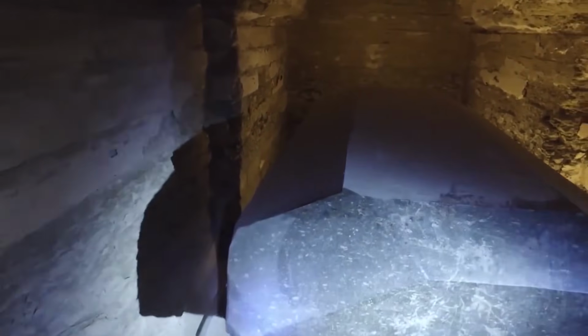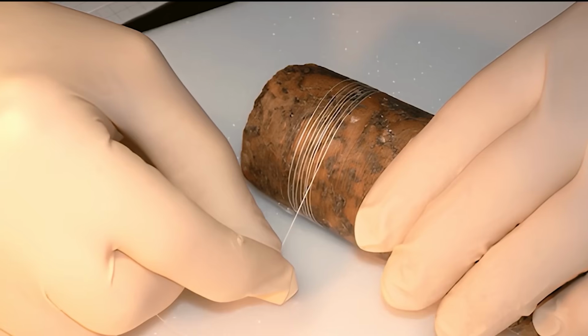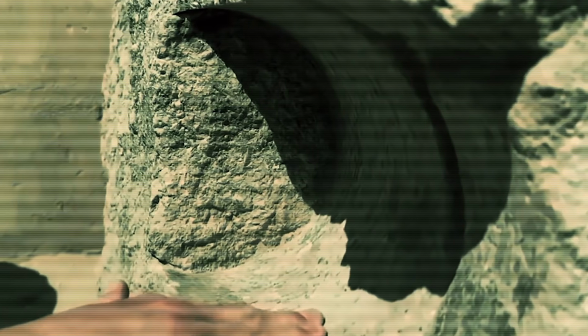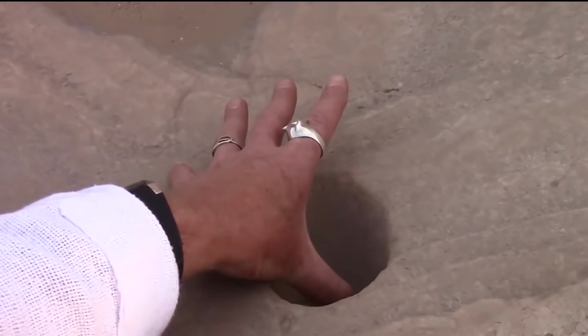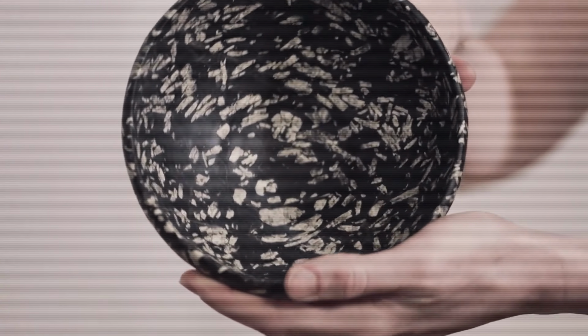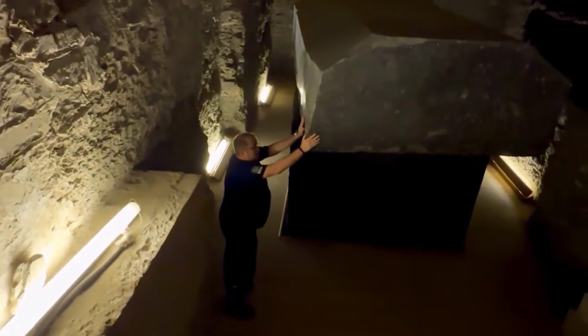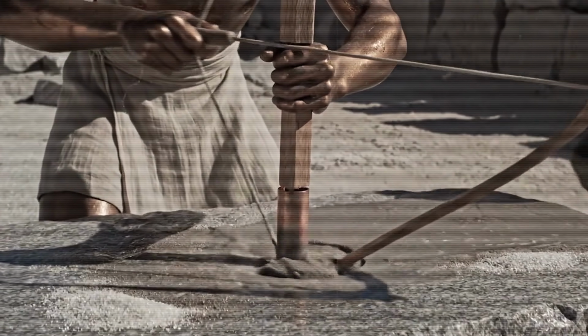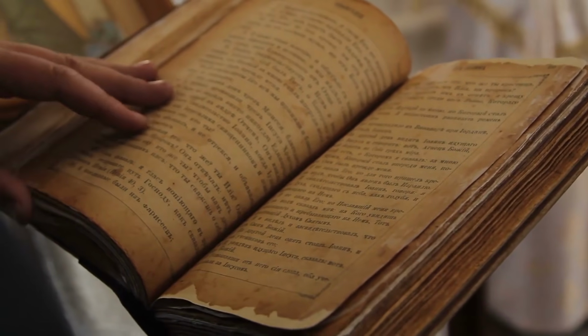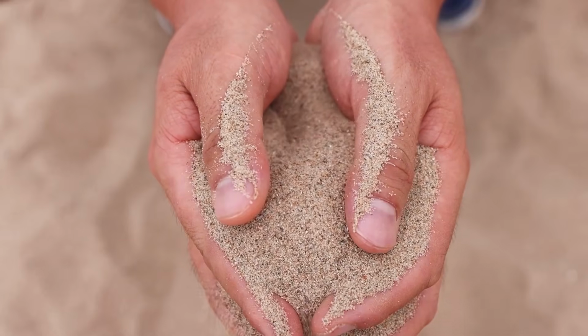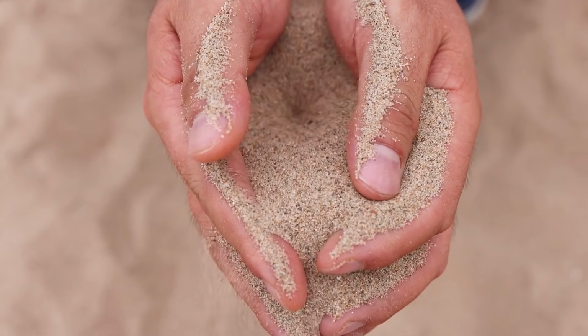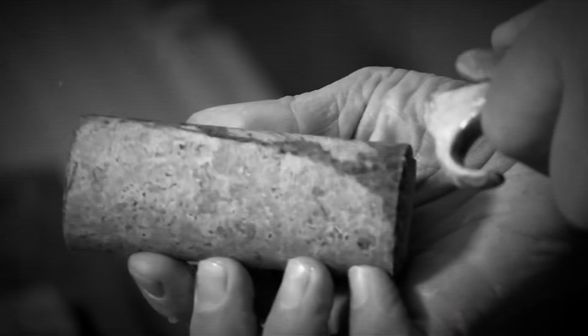What the experiment also revealed was that the corundum method required real skill. The slurry concentration had to be maintained within a specific range. Too thin and cutting efficiency collapsed. Too thick and the groove clogged. Pressure had to be even, temperature managed, consistency sustained. In the workshop trials, the team found that the optimal corundum particle size was between 100 and 150 microns, fine enough to maintain consistent contact with the granite surface, but coarse enough to hold its cutting edge through multiple passes. Getting the mixture wrong by even a modest margin produced cuts that degraded toward the same roughness that sand abrasion leaves. Getting it right consistently across the hours or days required to hollow a sarcophagus or core a shaft required a level of trained muscle memory that only sustained practice produces.